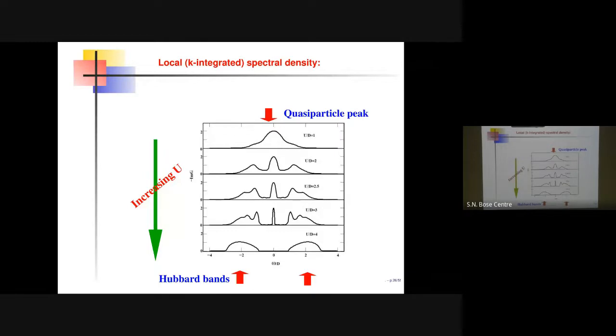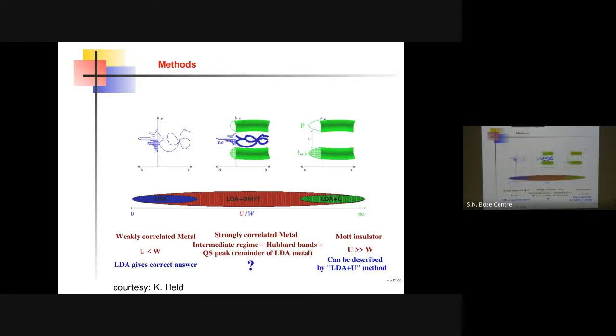If you just have a simple Bethe kind of lattice and do the dynamical mean field theory calculation, and just increase the strength of this Hubbard U, then starting from a non-interacting density of states, you can get to a Mott insulator, but passing through something known as a correlated metal, because it has the signature of the Hubbard band, as well as what is known as a quasi-particle peak. In fact, someone asked during Manisha's talk about the satellite and all that. Very often this is called incoherent and this is called coherent when you are doing any photoemission experiment.